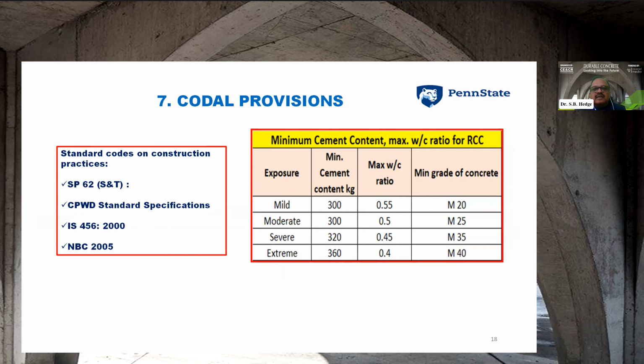And if you see the other slide, I have shown the minimum cement content and maximum water cement ratio for RCC for 4 different types of environmental conditions: mild, moderate, severe, extreme. What should be the cement content and what should be the water cement ratio for which grade of concrete? Everything has been shown.